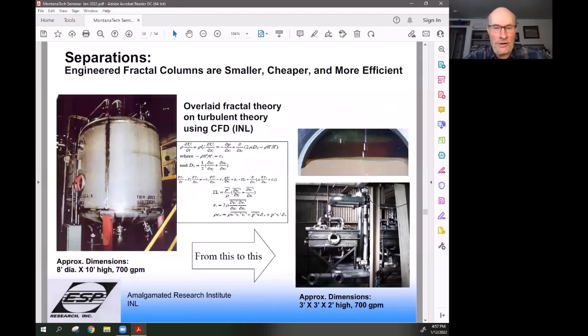We engineered a fractal column where we took the column and turned it into that box, which is 3 feet by 3 feet by 2 feet, running 700 gallons per minute through it, using engineered fractals. And in that upper photograph on the right, you see the clear rinse water over the juice, which is pretty dense, kind of brown, over the top of the solid phase exchanger. And that's running at 700 gallons per minute, constantly pushing it through. It ran for at least 4 years that I know of. And last I knew it was still running with water at temperature 90 degrees centigrade. So it was accomplished where you could run very hot solutions and not have to cool them before you hit the ion exchangers. Next, please.